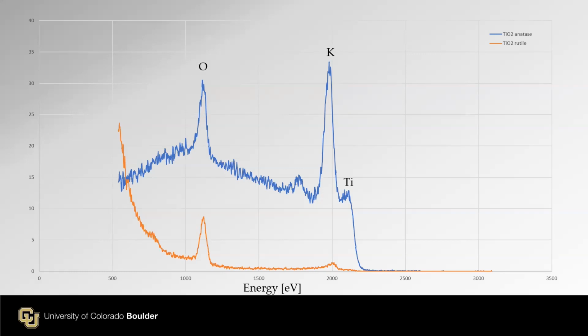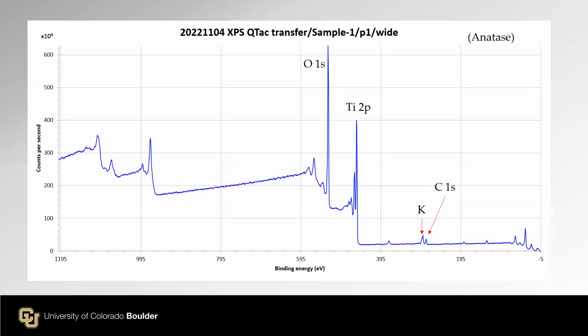Okay, so this is the LEIS spectrum for TiO2 anatase phase, 99.8%. And I put this same sample with the atomic oxygen cleaning, so I transferred from LEIS to XPS. And this is the XPS spectrum of the same reference sample. When we see this one, yeah, we have a TiO2 with a small contamination of carbon and small contamination of potassium. But I can go back.